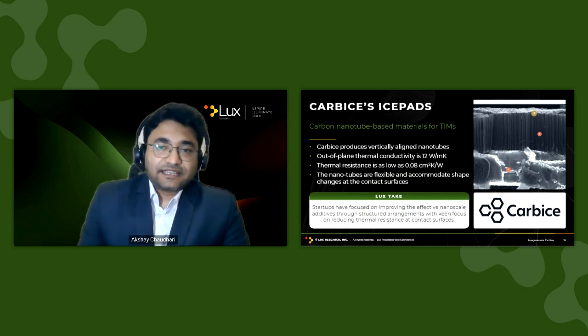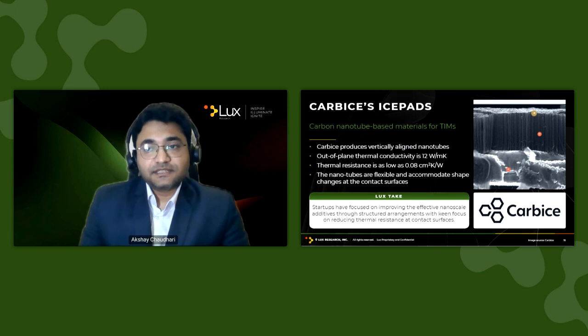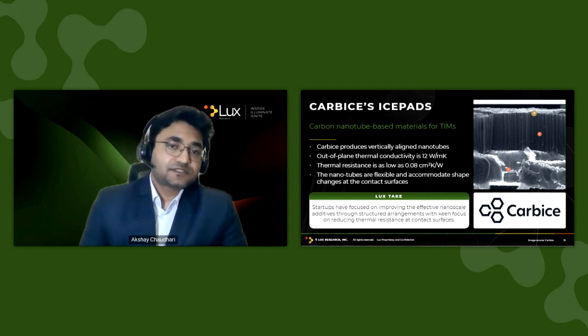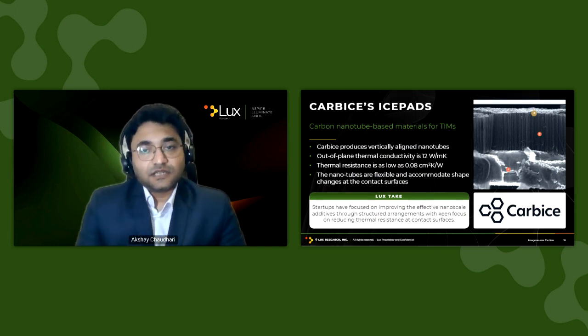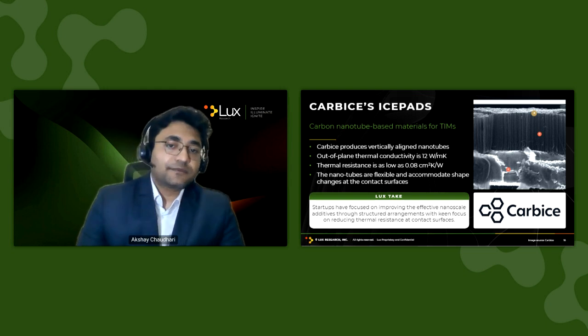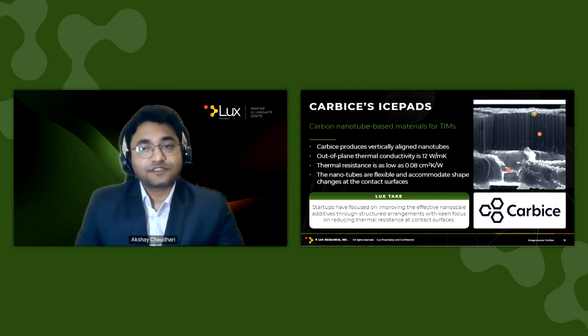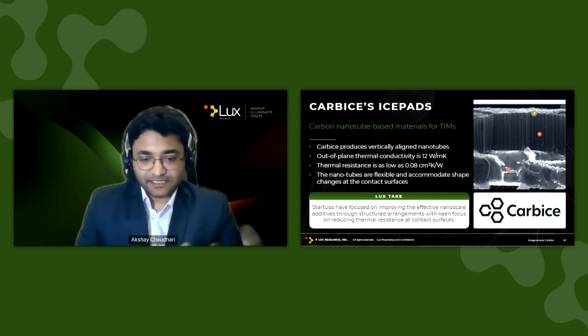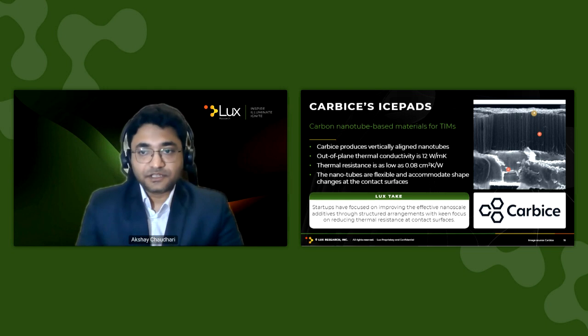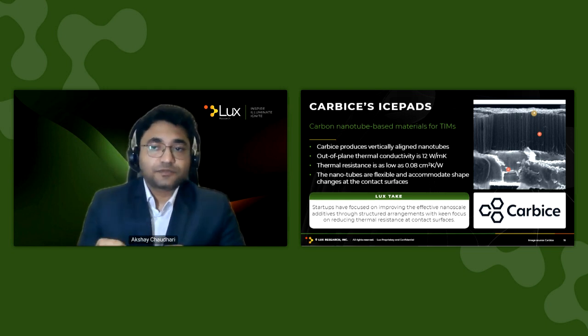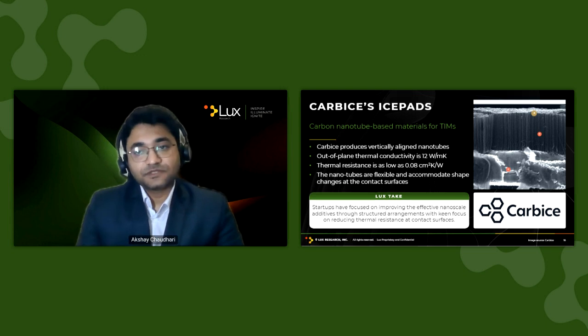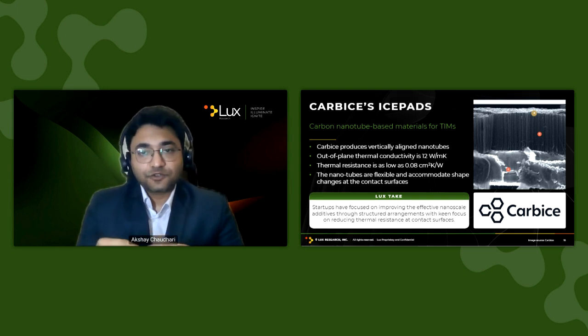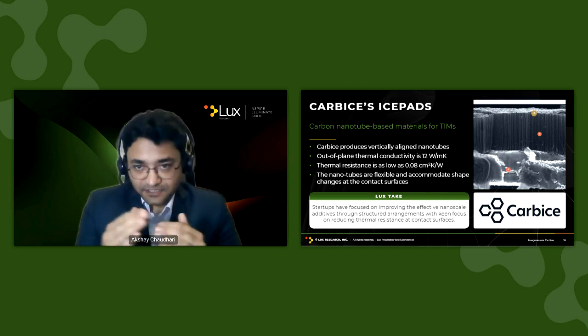Now let's take the example of Carbice, a company that develops nanotubes, and it uses vertically aligned carbon nanotubes in its TIMs. Carbice initially focused on thermal management for satellites, but for a couple of years, it has also expanded into electronics applications. Besides their high out-of-plane thermal conductivity, the key advantage of these vertically aligned nanotubes is low thermal resistance. This is because the nanotubes are compliant, they adapt to the surface deformation and ensure consistent thermal contact.